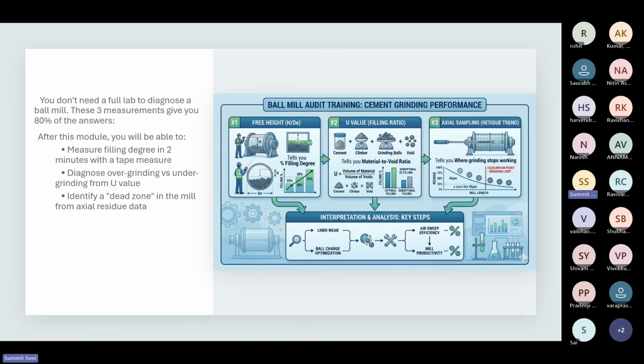These three measurements that you can see on the screen right now can give you 80% of your answers. What is the free height inside the mill? That will tell you the filling degree inside the mill. It's very easy. You just take a tape, put it on the material, go to the top of the mill, and see how much the height is. Second thing, the filling ratio based on voids. Whether your ball charge is expanded or not will also tell you how your mill is operating.